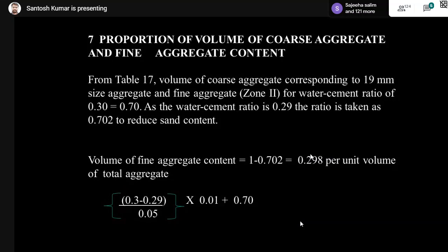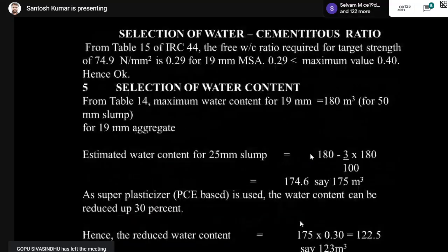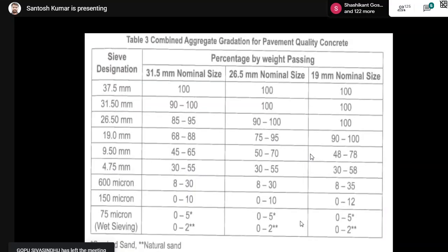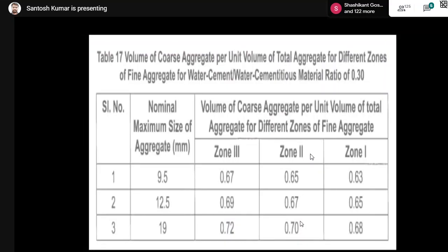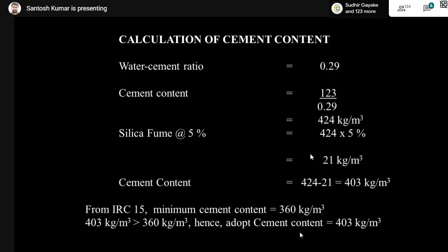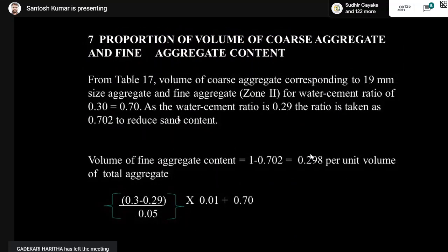And coming to the proportion of volume of coarse aggregate and fine aggregate content. As shown in the earlier slide, table number 17, the volume of coarse aggregate corresponding to 19 mm size of aggregate and fine aggregate conforming to zone 2 for water cement ratio of 0.30 is 0.70. If you want, I can take you back to the slide. Yes, you can see here, this is the volume of coarse aggregate for a water cement ratio of 0.30. Zone 2 sand, 19 mm aggregate, it is 0.70 as per the table. That is what we have taken in the design. So here it comes as 0.70.